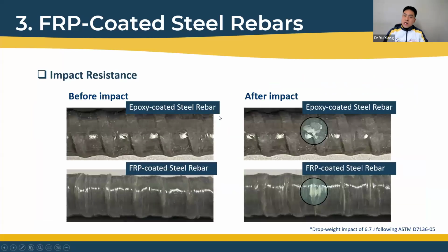As mentioned before, coated steel rebars, including FRP coated steel rebar, epoxy coated steel rebar, and other coated steel rebars, have to experience collision and impact during transportation and handling. We performed drop weight impact tests in accordance with ASTM standard.